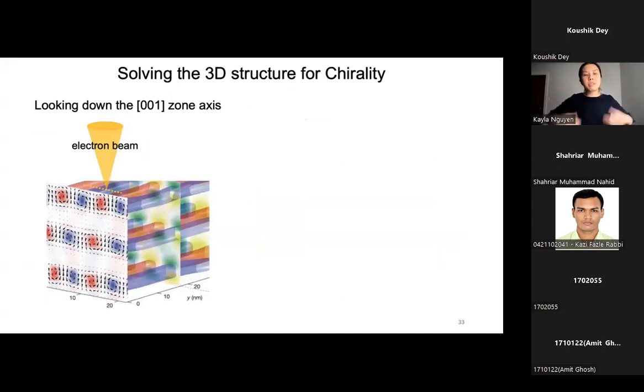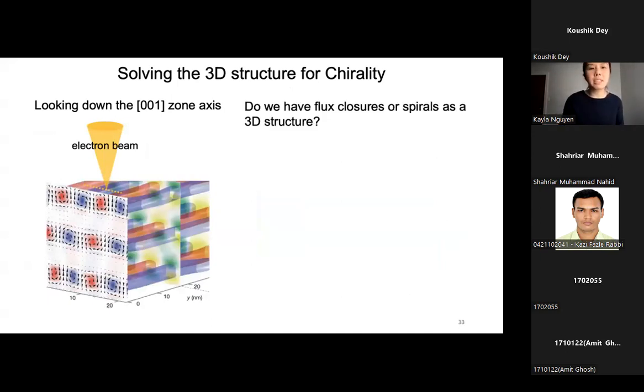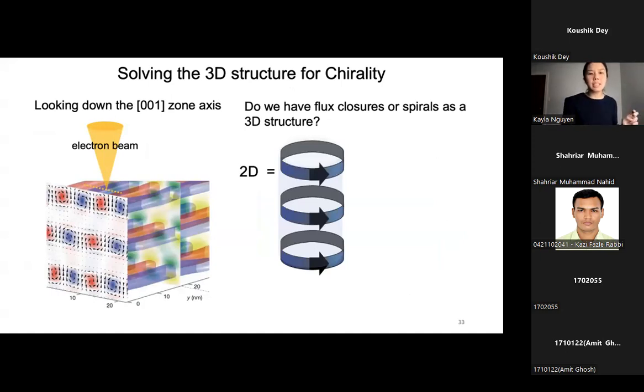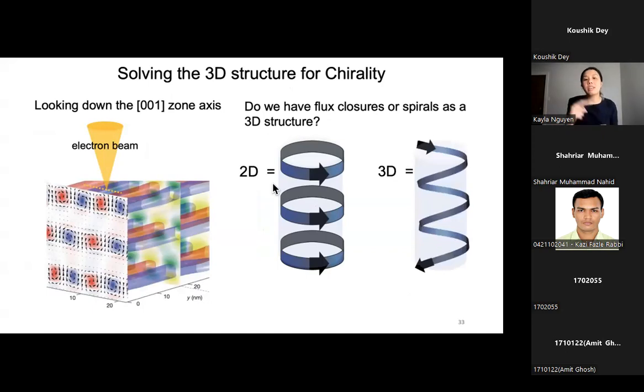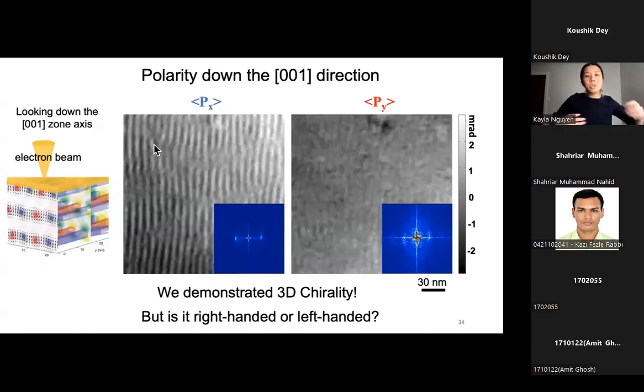If we're looking down the 0, 0, 1 zone axis for three-dimensional chirality, there are two different structures that we can get. If you take this structure and rotate it 90 degrees, it's going to lie horizontally. If our sample is two-dimensionally chiral, then what we should get are flux closures, these loops within this beam direction. If our sample is three-dimensionally chiral, then instead of flux closures, we should get a spiral. A three-dimensionally chiral structure means that we should get a signal for Px and Py looking down the 0, 0, 1 zone axis. And what we see in our sample is that we do get information down the 0, 0, 1 direction, where we get chirality in P. And so we find out that our sample is three-dimensionally chiral.